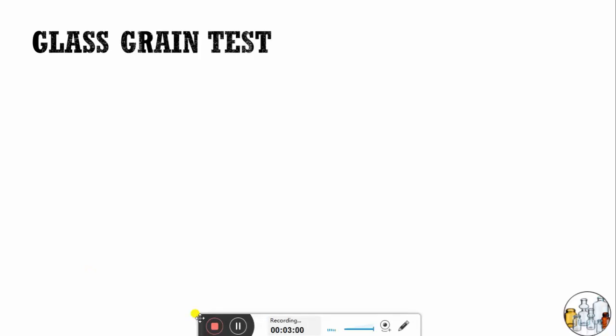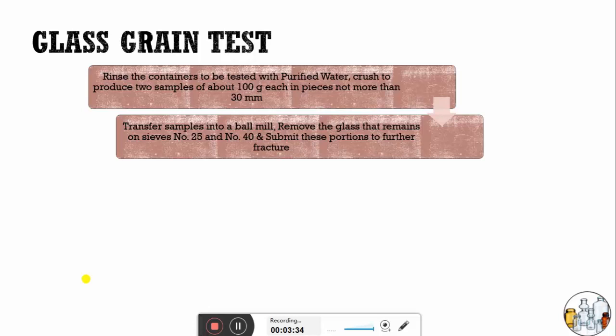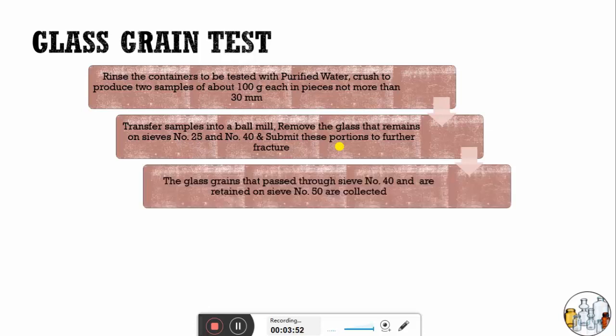For the glass grain test procedure — as the name indicates, the glass is broken and converted into grains, smaller particles. This test was previously given as the powdered glass test in USP. First, rinse the container with purified water and crush the product to produce two samples of about 100 grams each in pieces not more than 30 mm. These samples are transferred to a ball mill, then after crushing, passed through sieve number 25 and sieve number 40. Material retained on sieve number 25 is returned to the ball mill for further fracture.